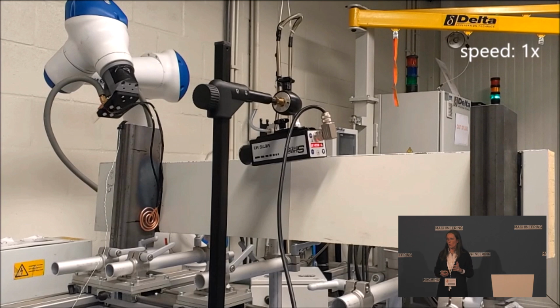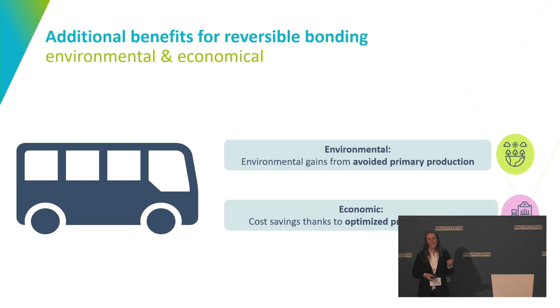So no external force is needed to achieve this, and this is achieved within 10 minutes again, or a little bit more than 10 minutes. It was 11 minutes. But you can also play a little bit with your settings of your induction heating. So we see that from a technological point of view, this is possible. But of course, is it also interesting from an economic point of view? And also from an environmental perspective, because this might be a nice circular solution fitting into the circular economy, but is it really interesting? Our partners at Vito did these calculations, this fully detailed analysis.